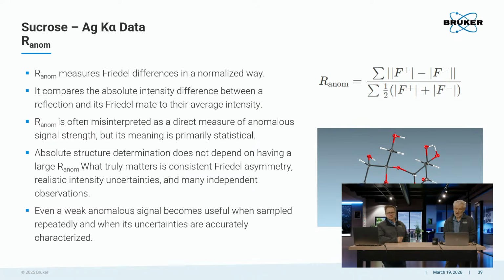So R anom is often misinterpreted as a direct measure of the anomalous signal, but it's really primarily a statistical tool. So what I want to say is that absolute structure determination does not depend on having a large R anom or a large difference in these Friedel pairs, although that helps. What truly matters is that the Friedel asymmetry is consistent over that long range.